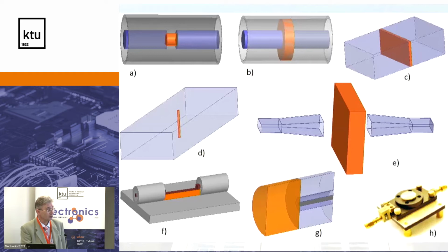Also, it can be an open-ended coaxial line, where you put the material at the end of the coaxial line and try to measure. The problem or shortage of this method, of course, all these methods have pro and contra arguments, and they do not fit for all parameters, for all materials, is that this requires a very good contact or a very clean and very nice surface of the material. And of course, resonators, like the split post resonator shown in the corner, where you can measure precisely the electric losses.